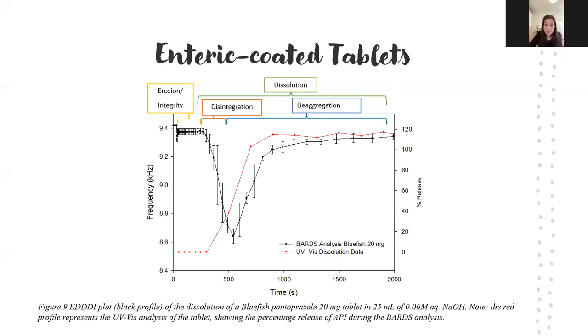The initial decrease in the fundamental curve is due to the entrained gas in the outer enteric tablet coating, followed by a subsequent return to the lag time during the erosion of the polymer. No pantoprazole is released during this lag time as demonstrated by the UV-Vis. Once the coating erodes and the inner tablet core disintegrates, there is an immediate release of that concentration of the API in solution, indicated by that downward slope to our F-min in the BARDS spectra. The end of the disintegration process is followed by the deaggregation of the tablet. And at that F-min, we actually have about 50% pantoprazole release, and that is indicated by our UV-Vis spectra. And then the frequency profile gradually returns to steady state in the BARDS spectrum during the deaggregation phase.